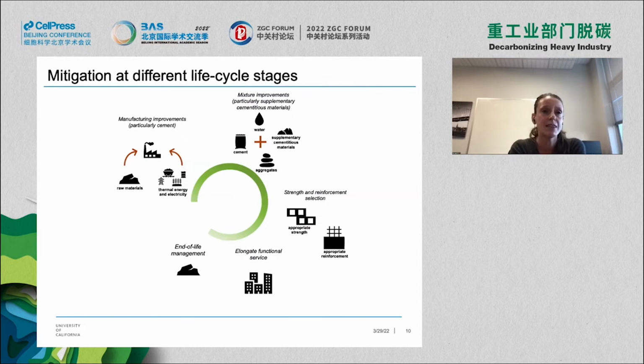Now, with that in mind, there are mitigation strategies throughout the life cycle, which I am happy to discuss in more detail in the panel, but just to give you some sense of what we've been looking at in our group, we do look at manufacturing improvements such as alternative energy resources, alternative raw materials. Of course, the alternative raw materials can then change some of our performance characteristics. We have looked at the materials design level. This includes things like how can we optimize the concrete mixtures that we're using such that we don't need quite as much cement? Are there alternative mineral resources that we could use at the mixture level when we're producing our concrete that again start to lower the amount of cement that we actually need?